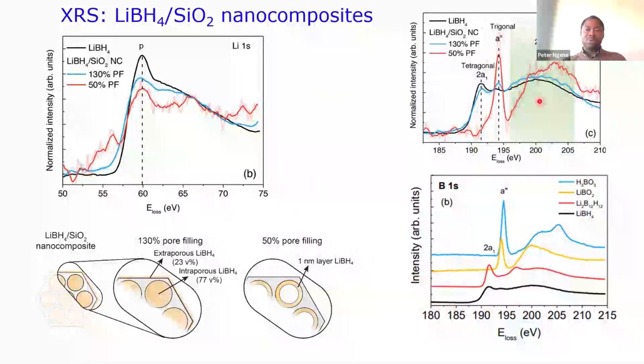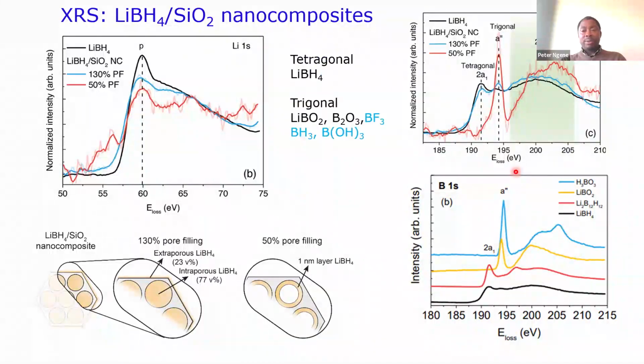And then we can see also that this extends to the transition region, which is also different. And of course, we try to do fingerprinting to figure out what is happening here, also combined with some calculations. But just to summarize, we start with the tetragonal lithium borohydride. So this gives us the tetragonal lithium borohydride. And then we do know that the transition around this 194 is actually trigonal.